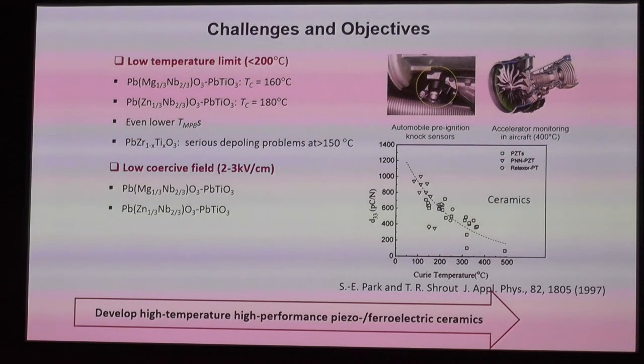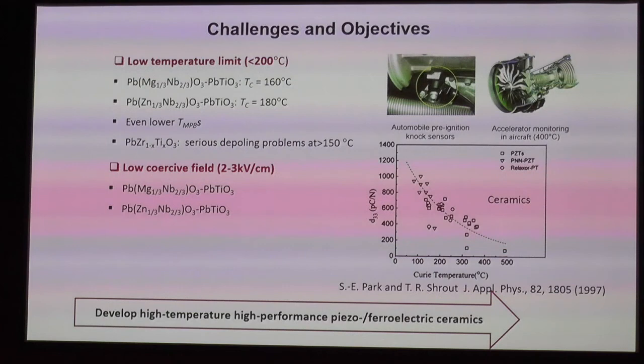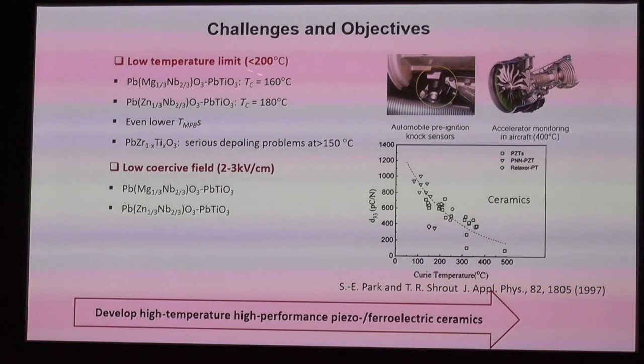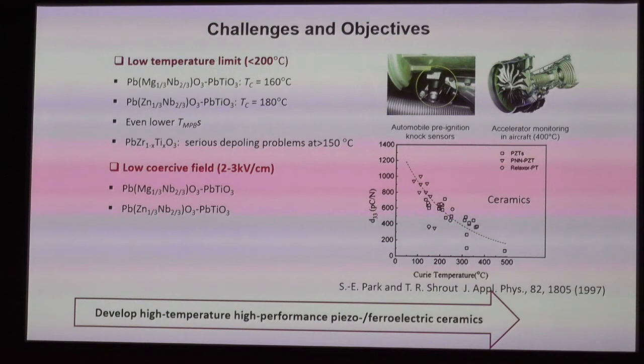But what is wrong with these crystals? What is not good? First, they are crystals, thus they're expensive, hard to prepare, and the same compositions in ceramic state usually have much lower piezoelectric properties. The other problem is that they work at low temperatures because the Curie temperature is comparatively low, and what is more important, they have a morphotropic phase boundary, and a phase transition between two phases at a temperature lower than the Curie temperature. And of course, if you have a phase transition, the domain structure changes, and it is impossible to heat the crystal above this